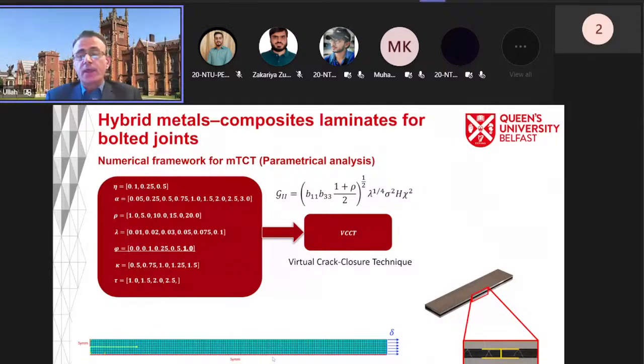And then the end result will be this X here, which is the correction factor, and this psi, which is what we call the mode mixity. So the results, as you can see here, are for different parameters, these material parameters. And here we are plotting this mode mixity with this alpha. So alpha is the length of this crack here, as you can see in this figure.